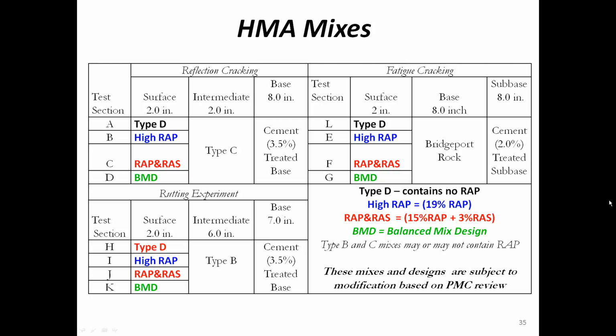I have noticed in some of my past projects that the ranking of mixes in terms of fatigue performance changes if you test those mixes at low strain or at high strain. That's right. Even in big beam fatigue tests, it will show you that. And that's a different type of strain than in an overlay tester, but the standard test method, I think, is something like 40,000 microstrains, where you're at several hundred microstrains probably in most of the work that you're doing on these sections. So that's a huge disconnect.